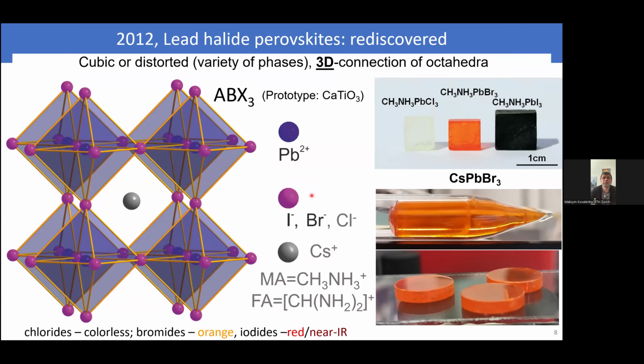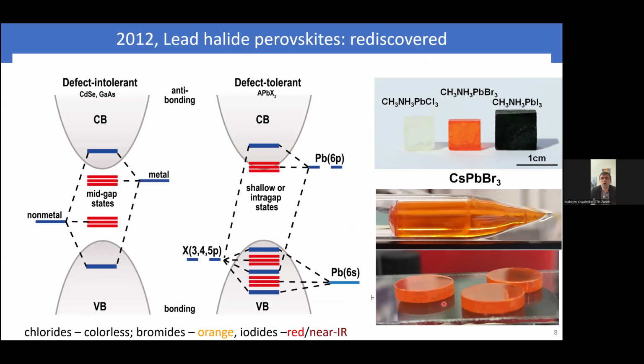And then here on the A side, which is the largest ion in the lattice, you have a choice generally of these three large cations: cesium, methylammonium or formamidinium. And so this is a relatively narrow compositional range, but still there is so much work being done worldwide, because with new semiconductors, people started to do all kinds of applications, from X-ray to gamma to photovoltaic. Actually, photovoltaics is the main, but also quantum dots. And this you can produce from solutions or from melt. We grow also bulk crystals and work on them in our team. But I will now talk about a probably more recognized invention in our team, which is quantum dots.